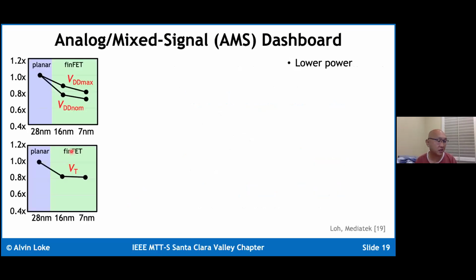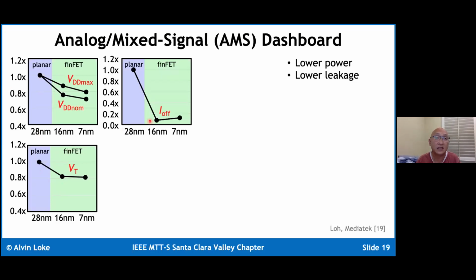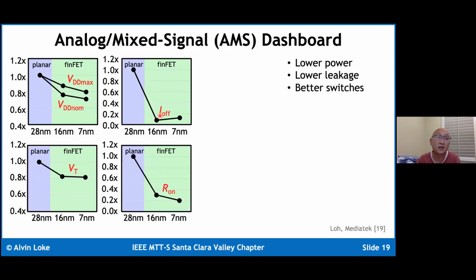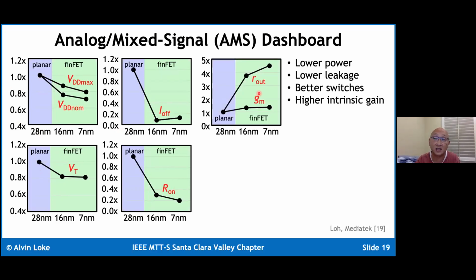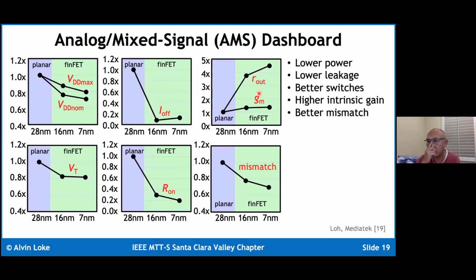Okay, so just looking a little bit at an analog mixed signal dashboard, for a planar device going to a FinFET, you can see that going from 28 to 16, we are definitely reducing supply, and also the threshold voltage has gone down, where the leakage has gone down substantially also. So this is all goodness. The on resistance has gotten better. You get better switches. You have better intrinsic gain, as I mentioned, due to reduced DIBL and also more mechanical strain. You've got better mismatch with less random dopant fluctuation. And you can do this all in a lower and smaller area, of course, in a more expensive process.